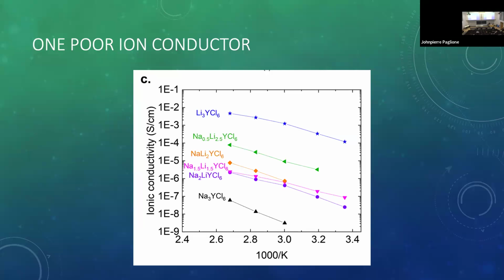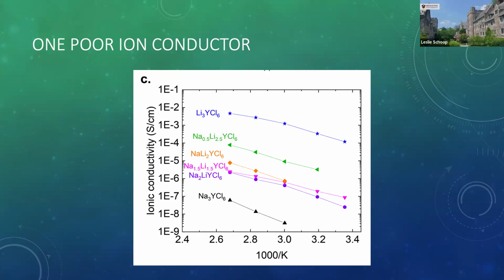And then they measured the ionic conductivities here, and up here you see the ionic conductivity of the lithium version, which is known and is a decent ionic conductor. And here's the sodium version, which was known to be a bad ionic conductor. And then, surprise, surprise, in between you get in-between ionic conductivities, and somehow this is being sold as great batteries and materials that were newly discovered by AI.